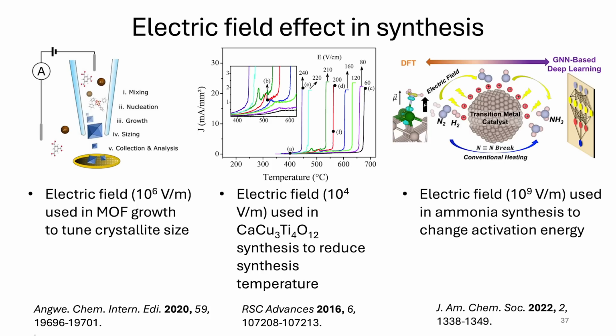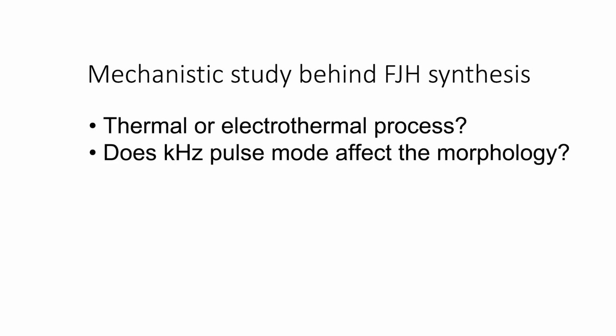What does the electric field do? Well, there have been a number of publications in the literature suggesting that an electric field can change chemical reactions. You can lower activation energies with electric fields. So we wondered, is this a thermal process or is it electrothermal, meaning the temperature plus the current going through the material? And does a kilohertz pulse, because we're often using kilohertz pulses through this material, affect the morphology? So what we did is we built two different systems.